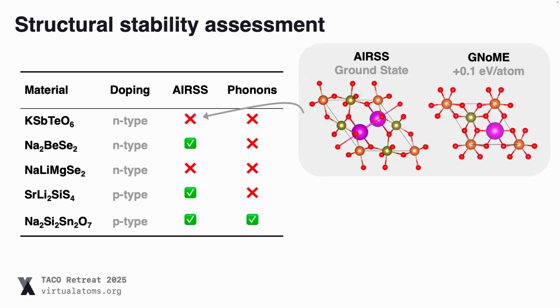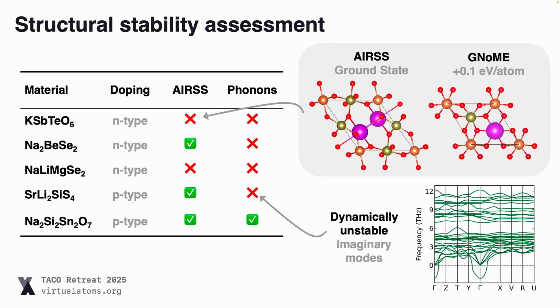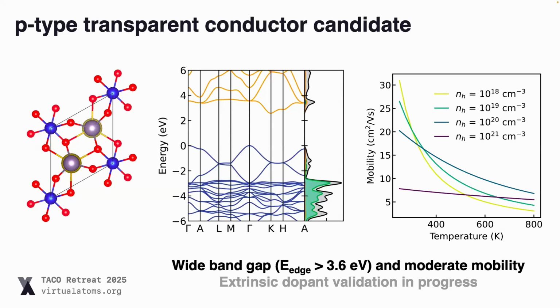The other issue is that we calculated the harmonic phonons, and we found that for most of these materials, these were not dynamically stable. So this is just an example where we had an imaginary phonon mode. We did try following these modes and trying to find the structure, but at the end of the day, we don't have very much trust in GNoME anyway. And so I think we need some way to filter these things out. If we're going to go to experimental collaborators, we want to have a lot of faith in the material that we're giving them, and making sure it's dynamically stable is a nice way of doing that. So anyway, this was the one material that came out.